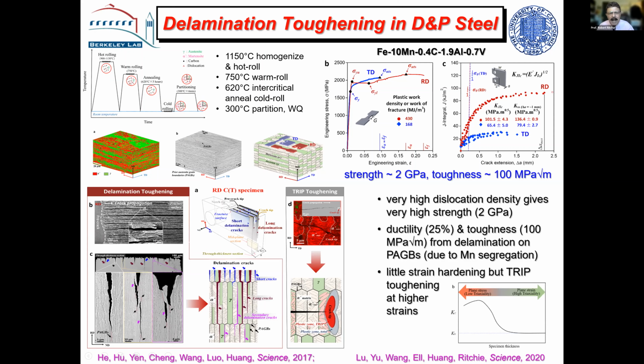There's quite a lot of things to do, but you end up with, again, a pancake type structure with these layers here, but it consists of both ferrite and austenite. And the austenite can TRIP to form martensite. So it's a bit of a TRIP steel. But if you look at the strength properties, these are the stress-strain curves, you get pretty high strengths here, about 2 gigapascals. And you don't get much strain hardening here, but you get a little bit of a rise there, and that's due to the transformation of the austenite to the martensite. And you can see an image of this here, not very clearly, but there is some transformation. But this is not the main effect, funnily enough.